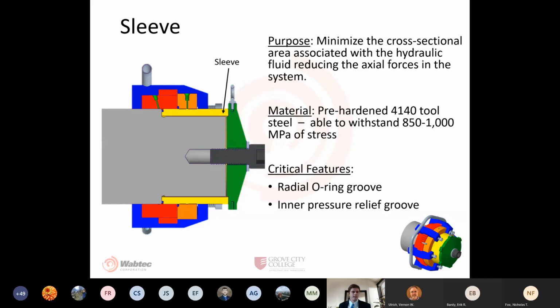Now, despite this reduction of axial force, the sleeve still undergoes a lot of stress, and to handle that, we selected a 4140 tool steel hardened to have a yield strength of about 850 megapascals at a minimum.